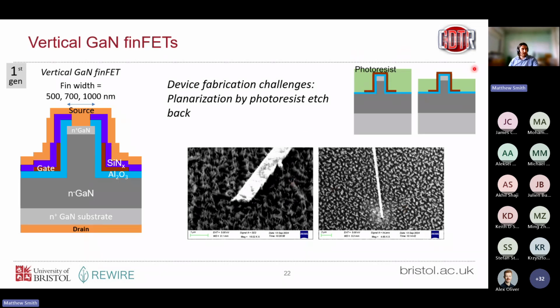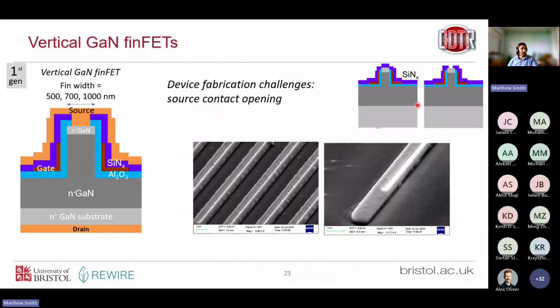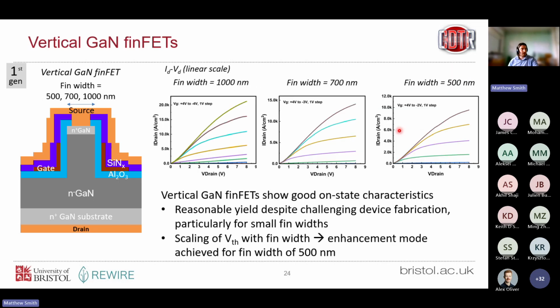This etch back process, very non-trivial, so trying to find a photoresist and an annealing and an etch process which just nicely exposes the top of the fin, and very challenging. Opening the source, very, very difficult. So these fins tend to be sub-micron, maybe 1 micron, and then we have to open a gap in a dielectric layer on top of this fin, and that gap you can see here is maybe a few hundred nanometers. So very challenging E-beam lithography alignment here. But yeah, credit to Chengji for doing great work there.